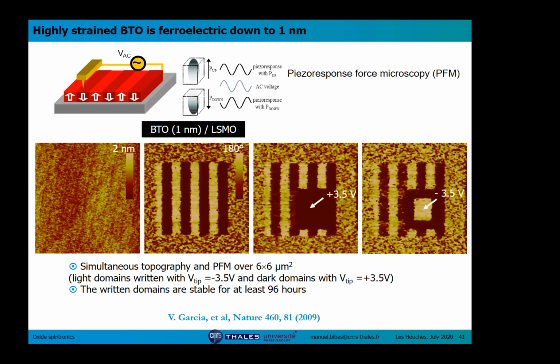And these are the results for a 1 nanometer thick barium titanate at room temperature. Here we had first applied voltages to pole the ferroelectric along these stripes, up or down. And you see when we read out the piezo response phase, we see a nice contrast with these clear stripe domains. And the phase contrast is the expected one, about 180 degrees. And we can write on top of this array and erase and write again. And this is stable for many days. So in principle, this is a good indication that the material is ferroelectric.